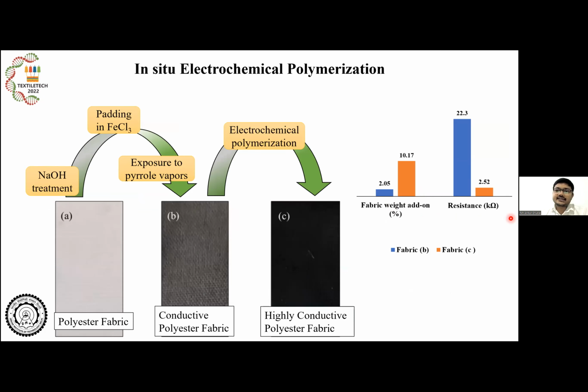So further, this study was taken over fabrics, polyester fabric. In the first step, this normal polyester fabric was converted to slightly conducting polyester fabric using the vapor deposition method. Since we cannot use normal non-conductive insulating fabric as anode or cathode in electrochemical polymerization, we have to do this step.